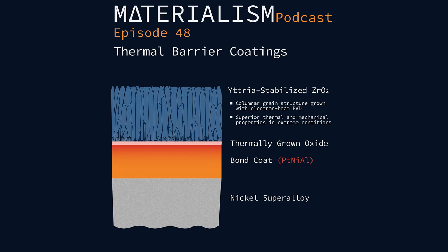Do you want to describe plasma spray for us, Andrew? To my understanding of plasma spray, essentially you're superheating some sort of material to a molten state, and then you're spraying it with high-powered pressure. It's a little more complicated than that, but you're essentially creating a molten material and spraying it almost in a hose-like fashion onto your material. Yeah, it says here about the plasma spraying process that the powders of the coating materials get fed into a plasma jet that's at obscene temperatures, 10,000 Kelvin, and then gets sprayed onto some sort of surface.